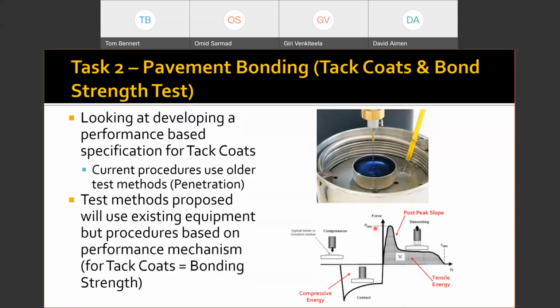So there's a couple of ways that we're looking at researching this now. One is to find a way to better characterize the materials that we use to bind these layers together, which are called tack coats. Historically, they've been tested with what is called a penetration test, where we push a needle into a sample. The deeper that needle goes in 5 seconds means it's soft. The less it goes into the material means it's hard. And there are certain requirements for what we call tack coats. But by no means does whether this material is hard or not dictate how it's going to perform in the field, how it's going to bond.